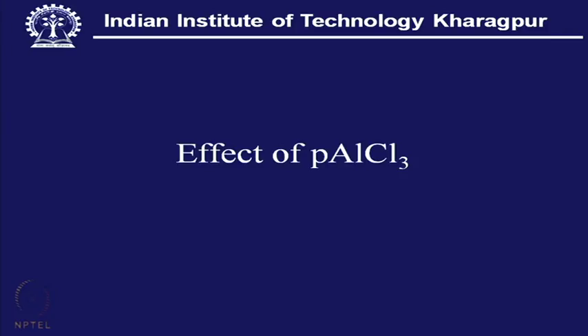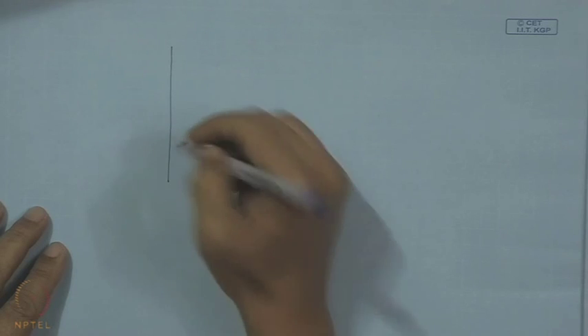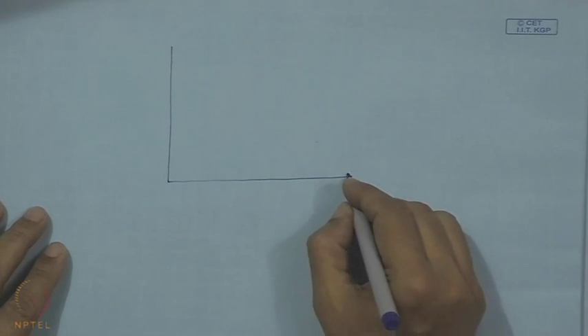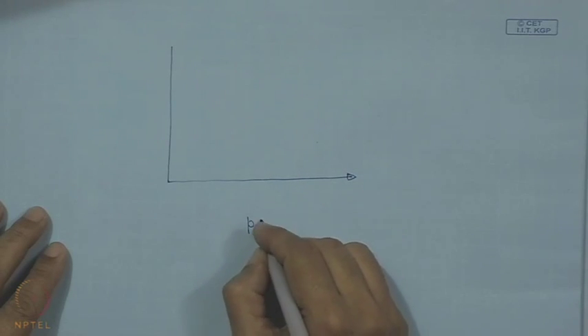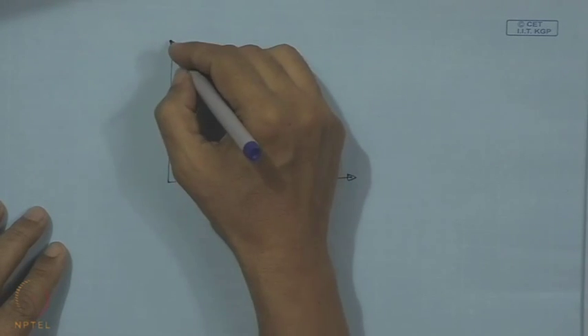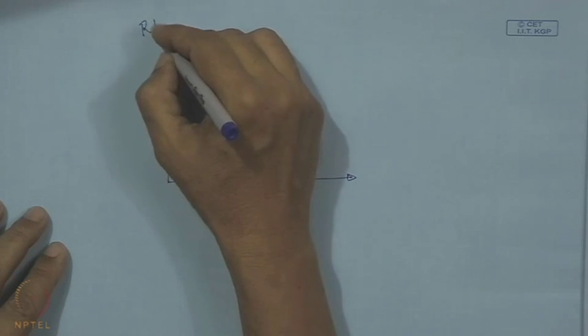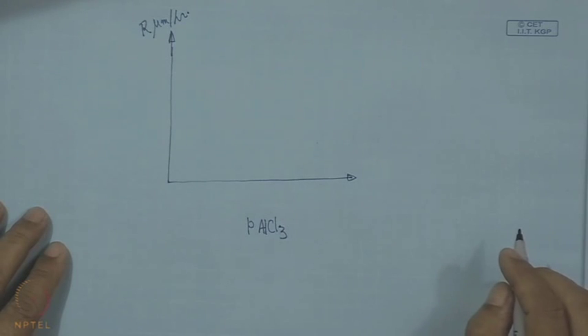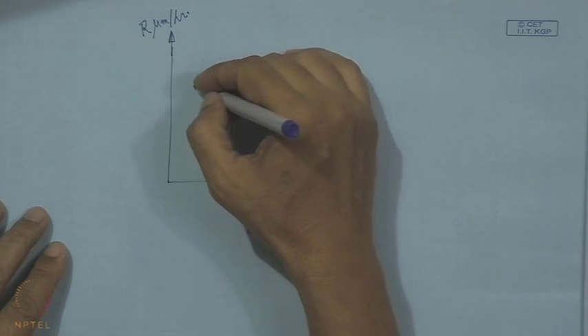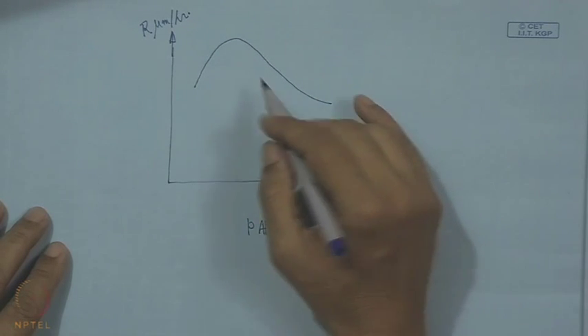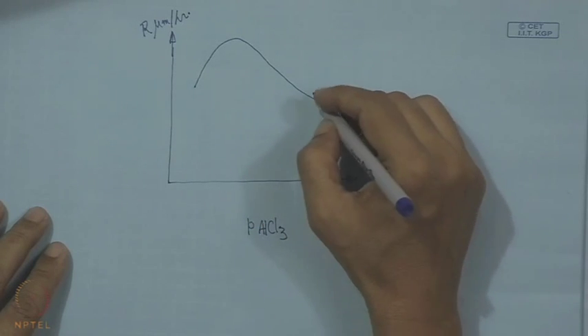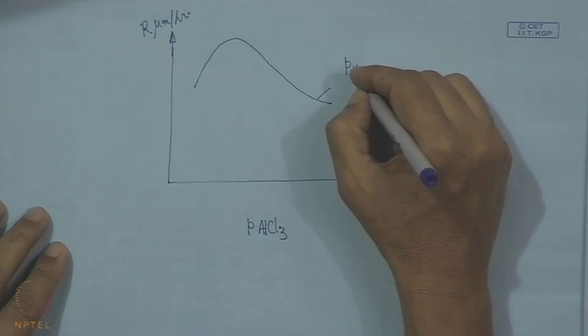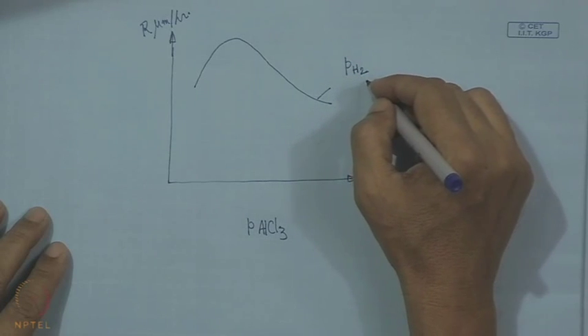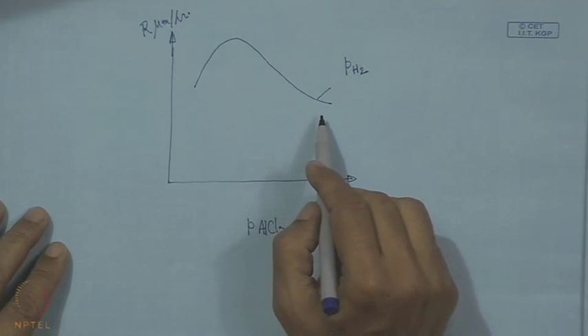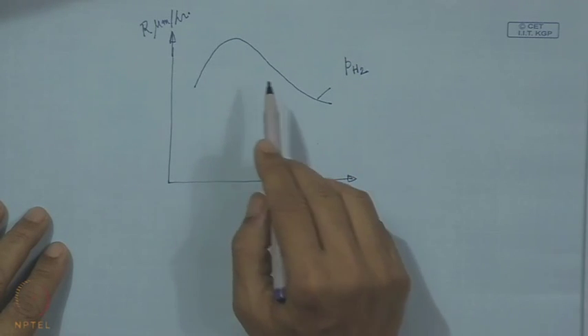Effect of partial pressure of aluminium trichloride. Now, this can be represented by this graph. This side we have partial pressure of AlCl3, and on this side we have R, the growth rate in micron per hour. Here the nature will be more or less like this, and this curve is valid for a particular value of partial pressure of hydrogen. By changing this partial pressure of hydrogen, we can have different locations of this curve, and it may also change its shape a little bit.